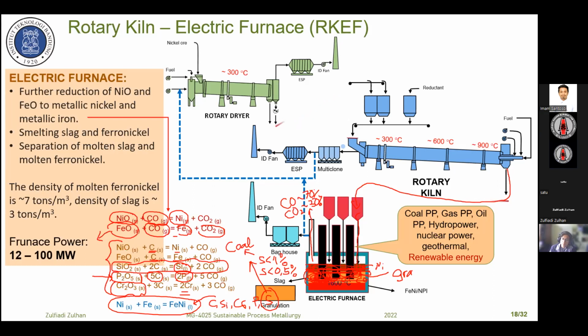We do not have, or we have only a small amount of CaO in the slag, so the desulfurization in the furnace we can say is less than 5%. In principle, it's difficult to conduct desulfurization during the process in the electric furnace, except if we add flux, if we add limestone, so we can remove sulfur from the metal.